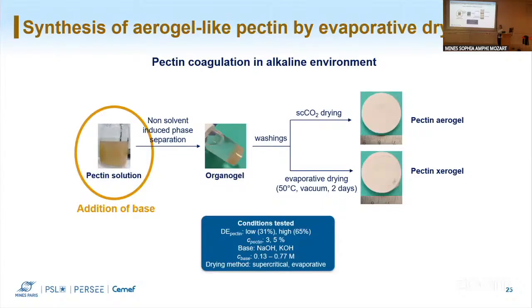Okay, but you agree that charge and your methyl esters are important here, right? Yes. The degree of charging, or the fact that you lose a charge when you decrease pH, for instance. Sure. That must be an important driver when chains associate to each other, right?